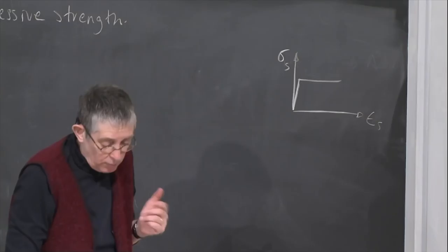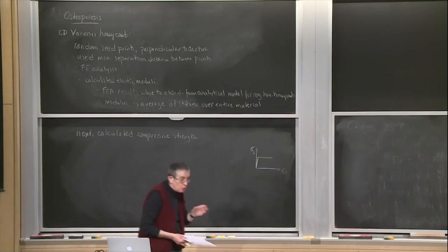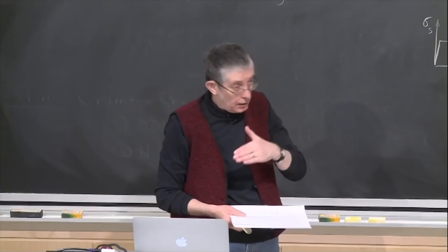And for that particular value, the transition between the elastic buckling and the plastic yielding failure was at a relative density of about 0.035. So then what we did was we analyzed structures that were a little lower than that, that were equal to that, and then a little higher than that. So we would try and see what happened with these different failure modes. And then we found